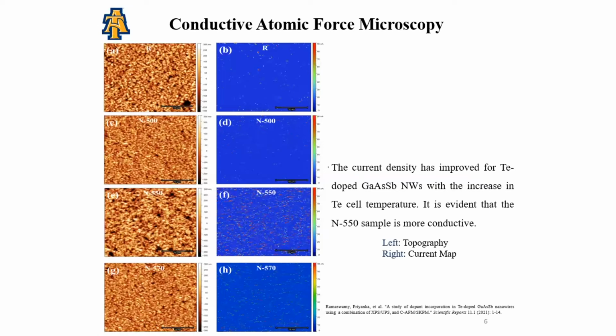In this, the left column depicts the topography of an array of vertically aligned tellurium-doped gallium arsenide antimonide nanowires, while the right column shows the corresponding current mapping of the doped nanowires. Here, N represents tellurium doping at the particular cell temperature. It is evident that the N550 sample is more conductive.